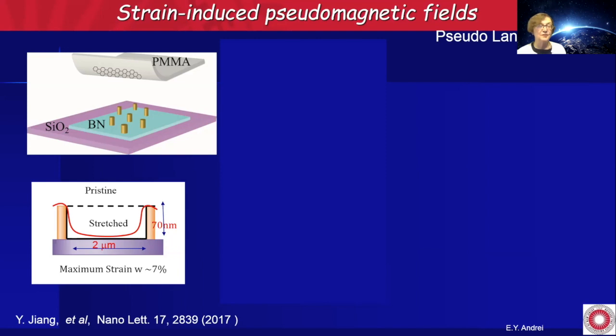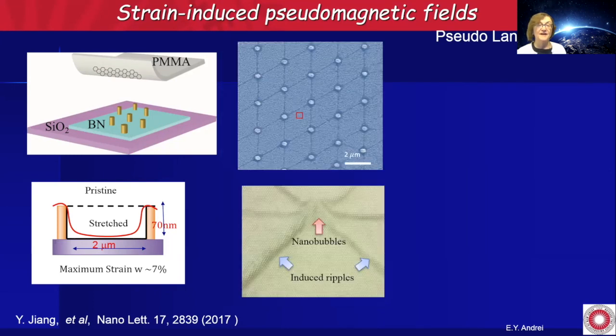You put a drop of liquid so that it really sucks into the substrate here. And what happens if you hold it in place at the edges, you will have huge strain that is building up here. And the strain pattern is whatever you want, depending on the pattern of your pillars. And also the strength of the strain depends on the aspect ratio of the height of the pillars and the distance between them. So here is what we get.